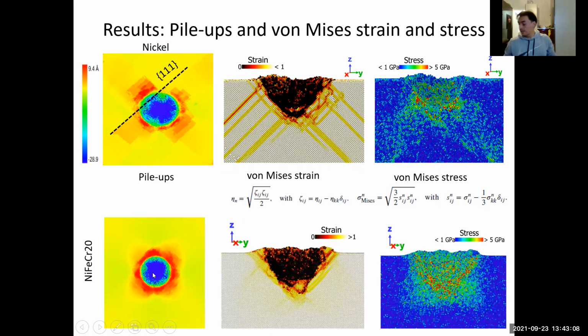And now, what is happening when you have 20% of chromium? The pile-ups are not even formed. You only have the clouds of atoms formed around the indentation, where the mark of the spherical indentation tip is. And then you have here the strain, where the maximum strain is underneath the tip, and also the shape of the von Mises stress for the maximum indentation depth, which is similar to the one in nickel when you reach 2 nanometers, only that it is scaled to 5 nanometers. To me, this is something really nice to understand, how this material is harder than the other material. This is really nice.